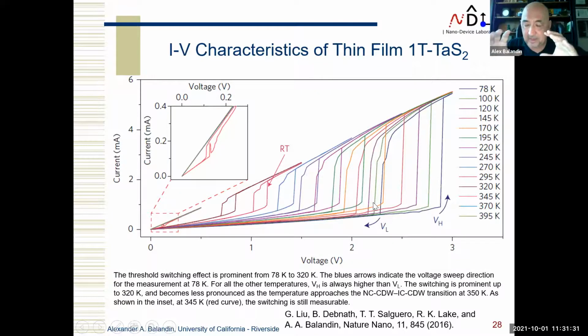And this is again my transition from commensurate to incommensurate, the one which appears at 350. So at low temperatures, the window is large. When you're increasing to room temperature, you still have a decent window. And of course, it disappears when you get close to 350.